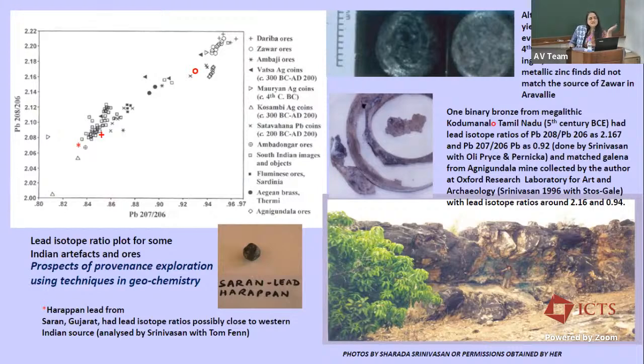But it doesn't vary from the extracted ore into the artifact, because when you're smelting metals, the elemental composition, of course, changes, but the isotopic composition doesn't change. So technically, in a particular lead artifact, you should be able to trace the source of the lead. That, of course, depends on whether the lead source itself has been analyzed and the isotopic ratios have been found.